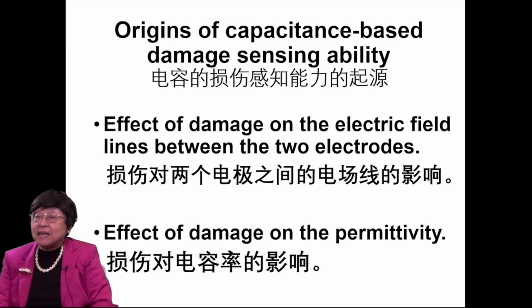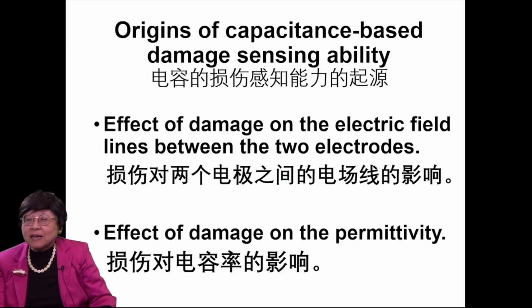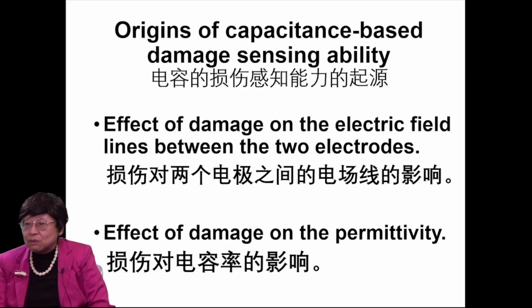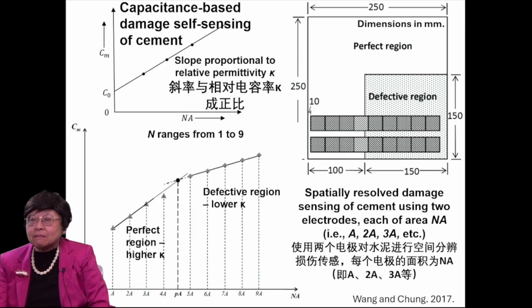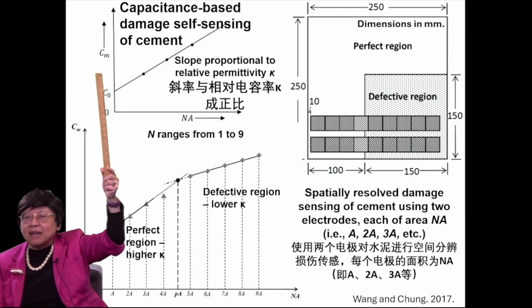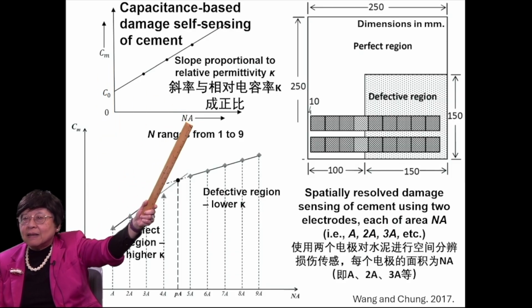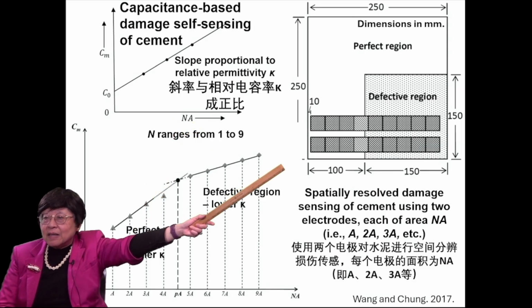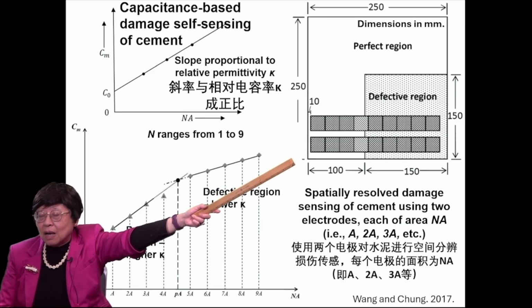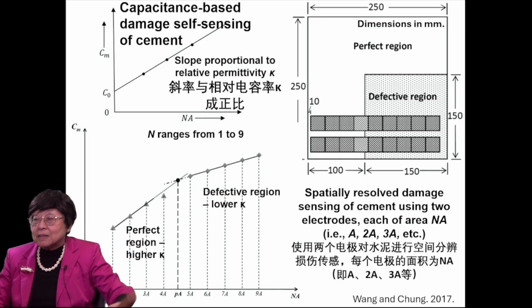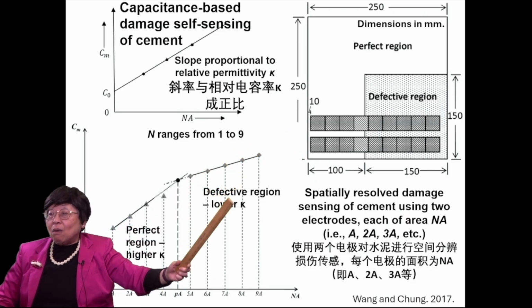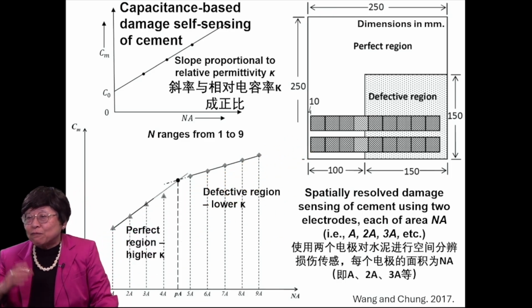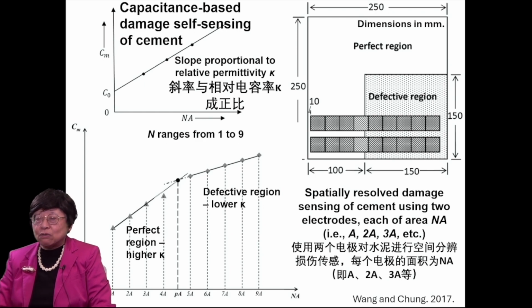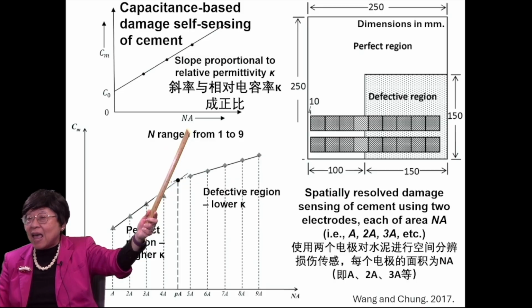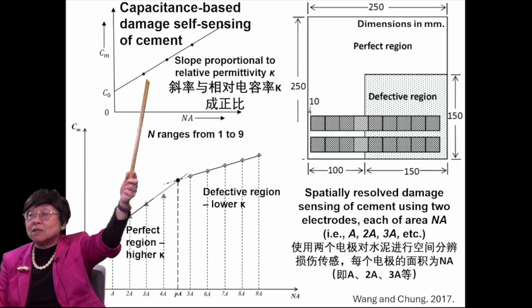The origins of capacitance-based damage sensing ability include these two: the effect of damage on the electric field lines between the two electrodes, and the effect of damage on the permittivity. Here shows the effect of damage on the permittivity, which can be obtained by plotting the measured capacitance versus the area being probed. And here we have two electrodes. Each has a number of segments, and we can have one segment, A versus A, or 2A versus 2A, or 3A versus 3A, or 4A versus 4A, for the two electrode strips. And so this capacitance is versus NA, and the slope is proportional to the relative permittivity.